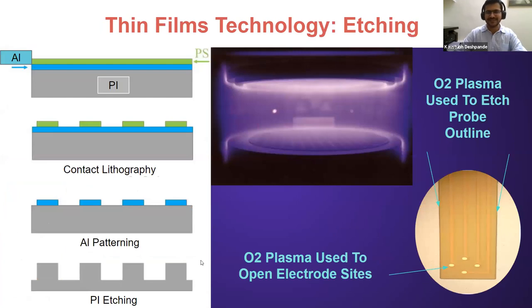Another technique, and this is a cool technique, is where we're using etching. Now, the challenge with etching polyimide is that polyimide and photoresist etch at the same rate in oxygen plasma. So if you have, let's say, 10 microns of polyimide, you need 10 microns or more of photoresist. Otherwise, it's just going to etch through the photoresist and etch into the polyimide. So what we do is we use something called a hard mask, where we put down another sacrificial layer, aluminum in this case, and then pattern the aluminum to make openings. So instead of having a photosensitive mask, you now have a metal mask, and then we proceed with the oxygen plasma etching. Beautiful color, right?